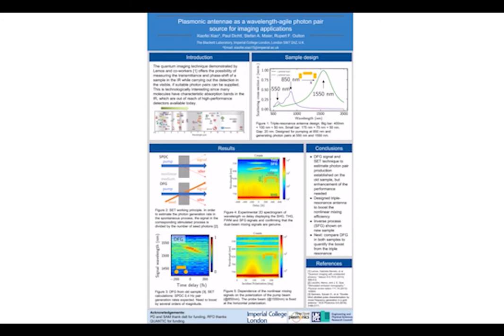So far, we could apply this technique to a sample that was used for nonlinear frequency mixing studies previously. The framework is established now, but the best we could get out of this old sample is an estimated SPDC pair generation rate of 0.4 Hz. So we want to use our new antenna to increase this efficiency.